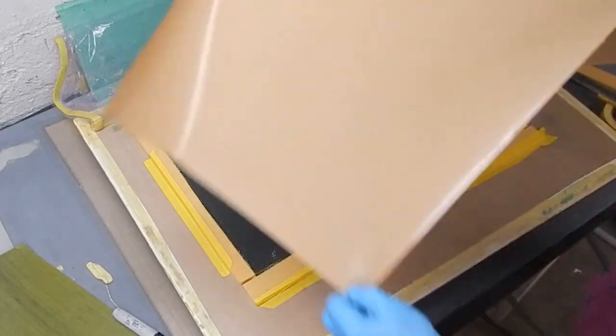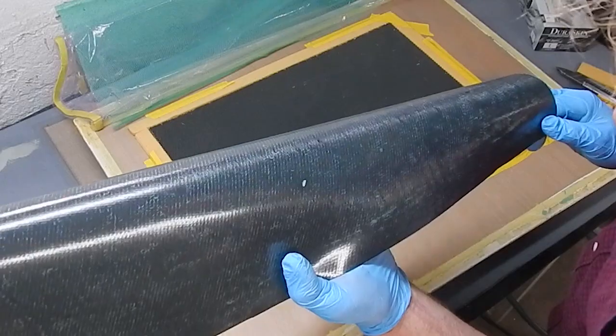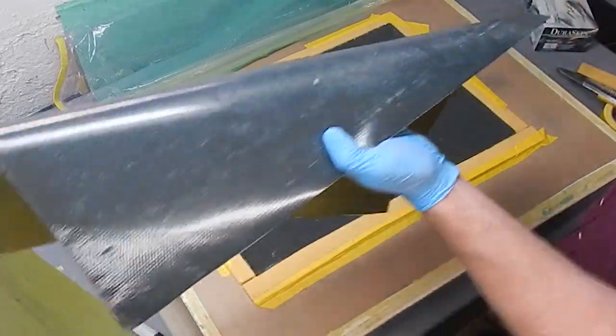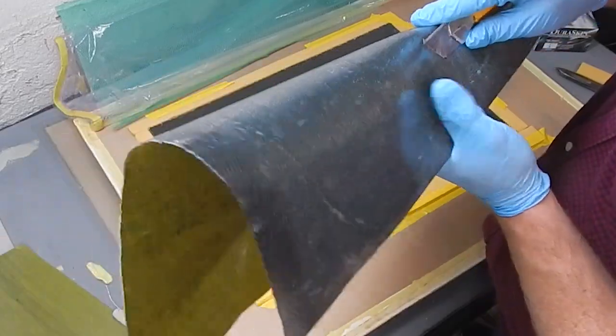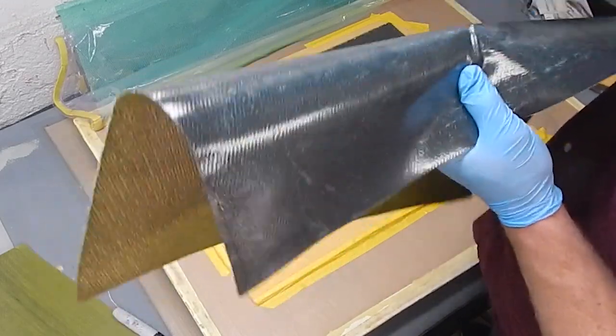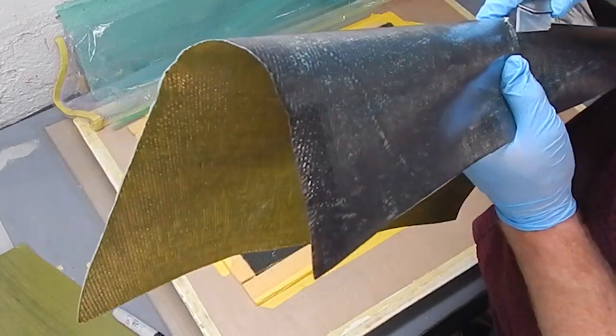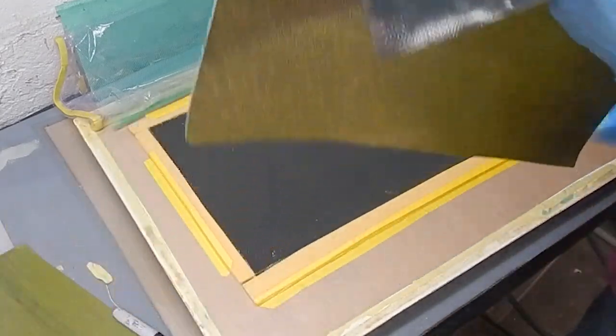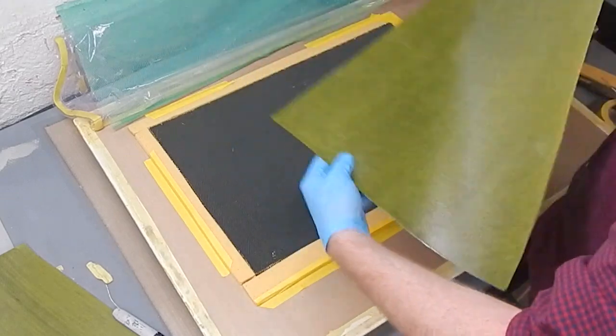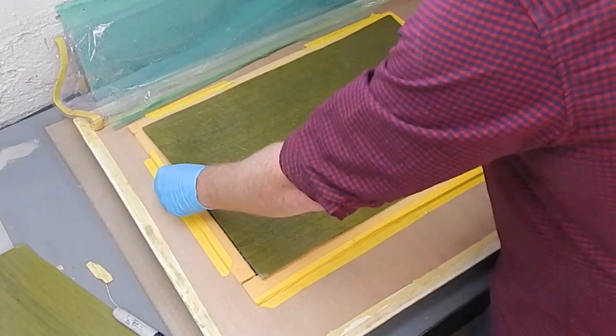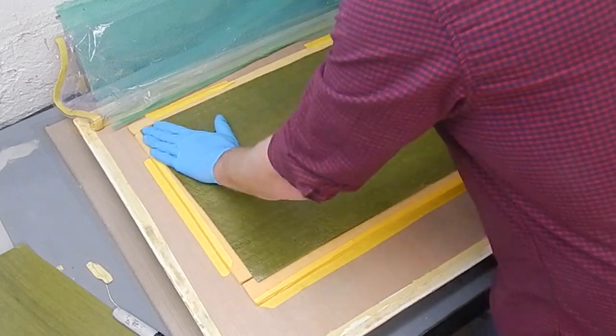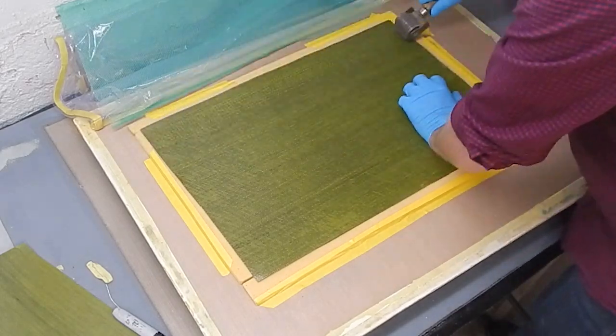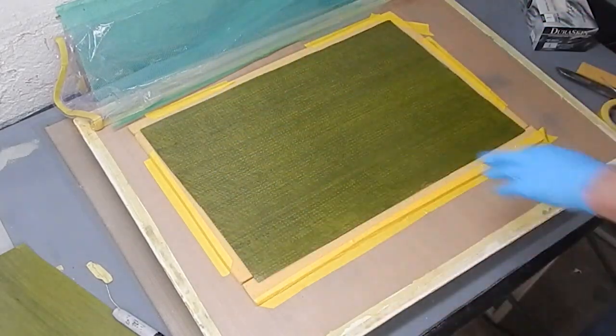And I'm just going to go ahead and put that top skin right on. There's a little bit of junk in there that I'm going to have to pull out that I must have got stuck between the glue film and the carbon when I did that first debulk. That is not as nicely stuck together as would be ideal. You can still see some air in there. A longer squish when I co-applied the glue film to the carbon would have been nice, and or more heat. But this is really just for demonstration purposes. And to get a sense of how this stuff works, I'm going to run the spiky wheel on there and give it another debulk.